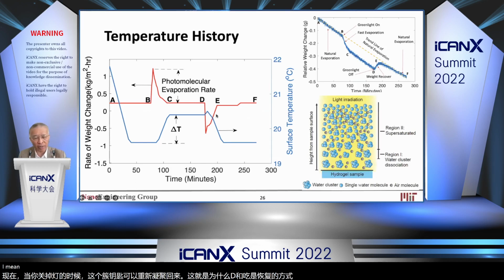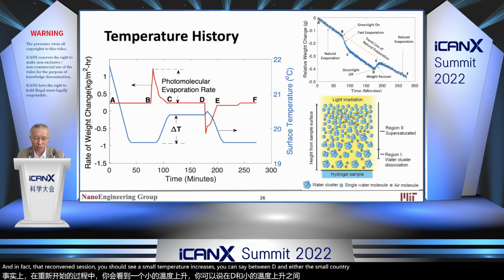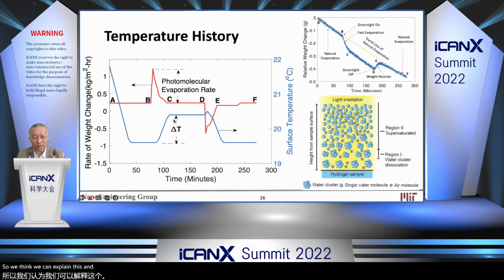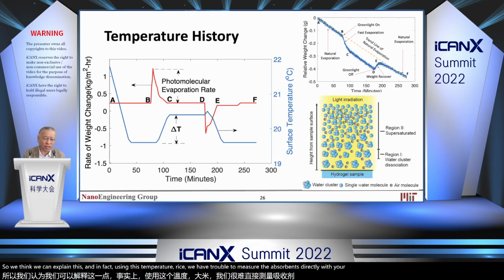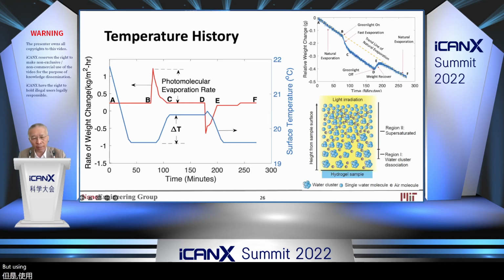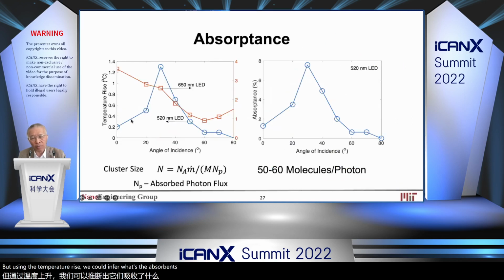And in fact, in that recondensation, you actually see a small temperature increase. You can see between D and E, there is a small temperature increase. So we think we can explain this. And using this temperature rise, since we have trouble measuring the absorptance directly, and we're still trying, we could infer the absorptance. So we measure the temperature rise. On the left-hand side, you can see the blue peaks at 30 degrees.